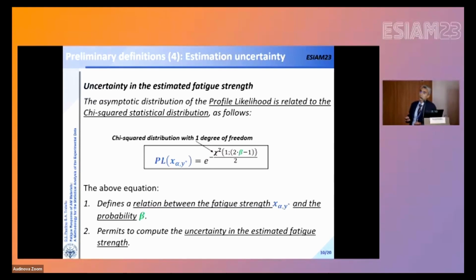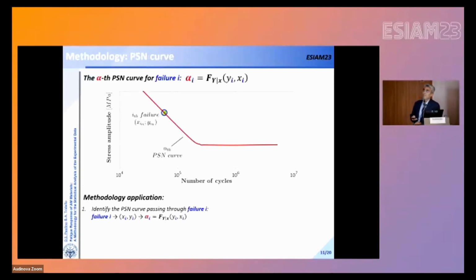Through this equation, you can define a relation between the fatigue strength and the probability beta. And this permits to take into account the uncertainty in the fatigue strength estimation. For a particular value of beta, you will have a particular value of the fatigue strength, and then you can take into account the confidence interval related to the fatigue strength that you have estimated. Then let's start with the application of the procedure.